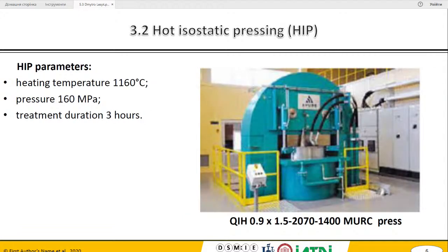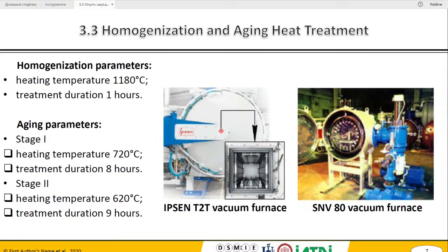To eliminate the internal porosity and increase density of material, all SLM built specimens were subjected to the hot isostatic pressing treatment. The heat treatment consisted of a heating temperature of 1160 Celsius degrees and a pressure of 160 megapascals for 3 hours. Next slide, please. Then the heat processed specimens were subjected to both a homogenization heat treatment, followed by double aging heat treatment according to a standard. In particular, the homogenization heat treatment was performed at the heating temperature of 1180 degrees Celsius for 1 hour using a vacuum furnace. The aging heat treatment parameters are listed on the slide. Next, please.